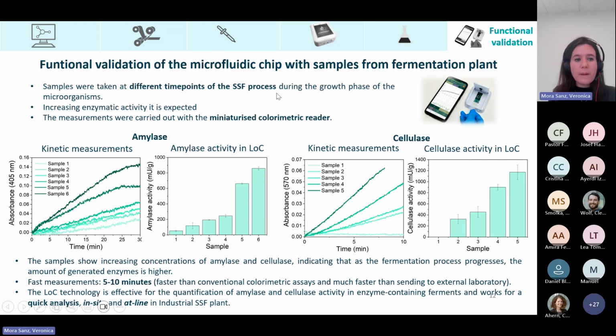Then we transform these kinetic measurements into enzymatic activity, and we can see that the samples show increasing concentration of both enzymes, indicating that as the fermentation process progresses, the amount of generated enzymes is higher. These measurements were quite fast because they only take 5 to 10 minutes. That is much faster than conventional colorimetric assays, and of course much faster than sending the samples to an external laboratory.